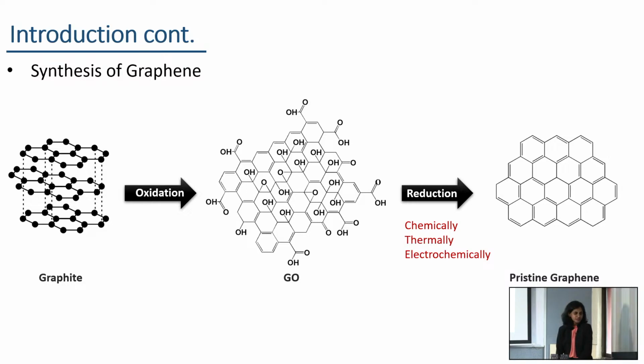As I mentioned earlier, graphene oxide is one of the intermediates of the chemical synthesis of graphene. During the chemical synthesis of graphene, graphite is oxidized into graphene oxide and then followed by reduction into graphene via chemical, thermal and electrochemical techniques. Here, obtaining pristine graphene through this reduction process, through the removal of all these oxygen functionalities, is highly challenging. So that is like a dream.